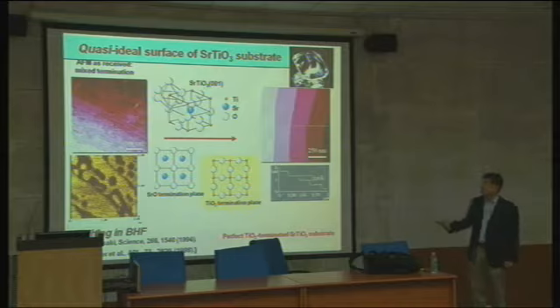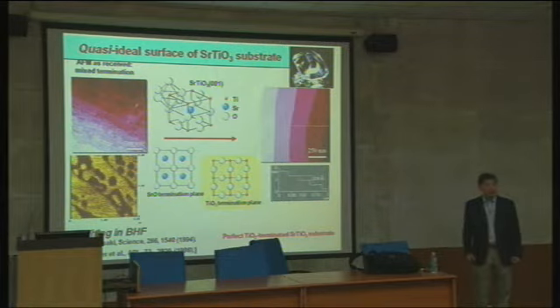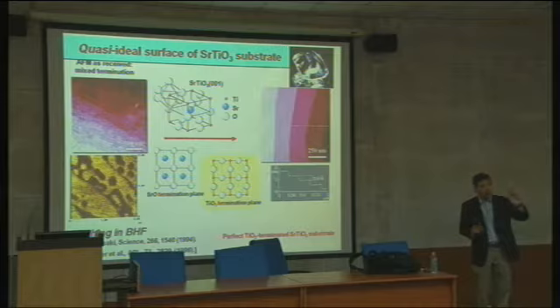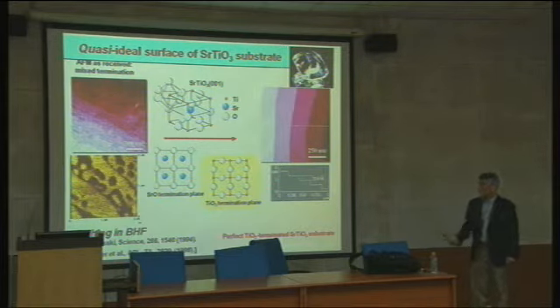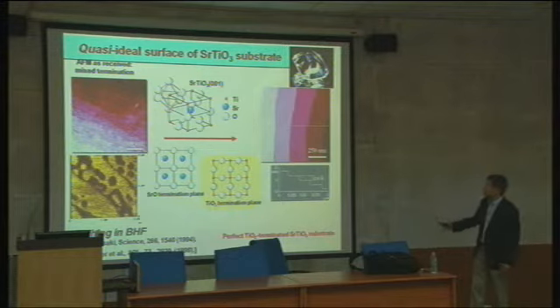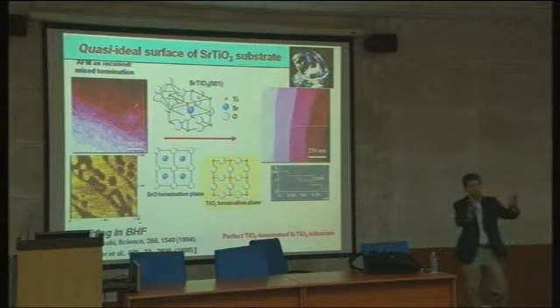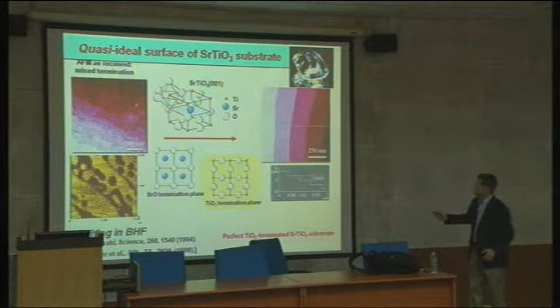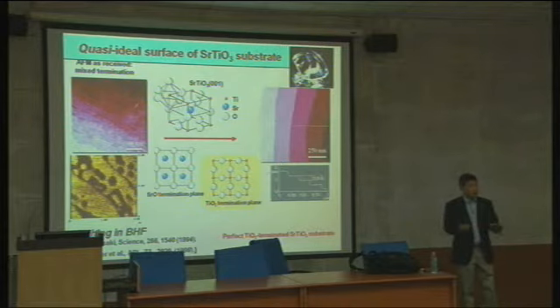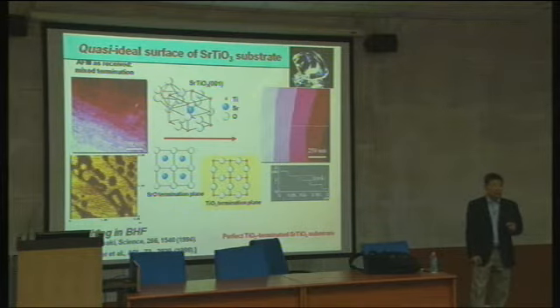And you do not see half-unit-cell steps. When you scan from here to here, strontium oxide to titanium oxide, those steps would be roughly 2 angstroms. So if you see 2 angstrom steps together with 4 angstrom steps, that is a mixed termination. But another important fact is that you have very well-defined long terraces. So at least in these regions, when you grow, there are no steps everywhere and a single surface termination. And that's the first important aspect: you make your material a single surface termination.